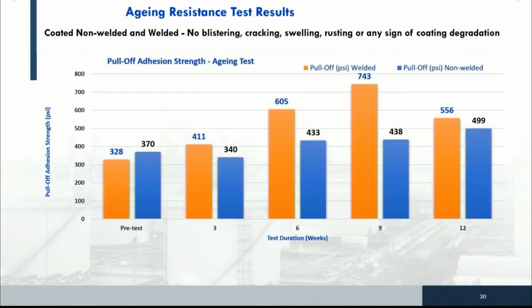We also observed there is no rusting, no blistering, no change of color, nor any sign of degradation for welded coated and non-welded coated. The only thing we can do here is to evaluate the coating according to pull-off adhesion strength. This figure shows the pre-test pull-off adhesion test of the orange, the welded, and the blue, the non-welded. As you can see, there is an increase in the pull-off adhesion, the same thing as we observed in the immersion testing, and the mode of failure also changed. However, for the non-welded one, it stayed almost constant.